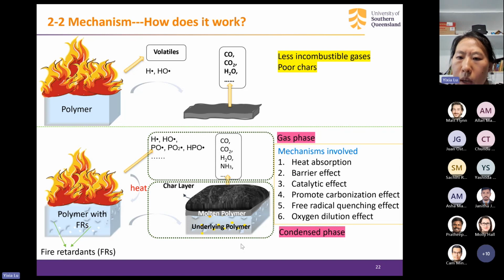So the mechanisms involved in this combustion include heat absorption, barrier effect. For example, the char layer as a barrier to isolate oxygen and the underlying polymer, and catalytic effect by the fire retardants, and promote carbonization effect, free radical quenching effect, and oxygen dilution effect. They both work in gas phase and condensed phase together, so the efficiency is much higher.